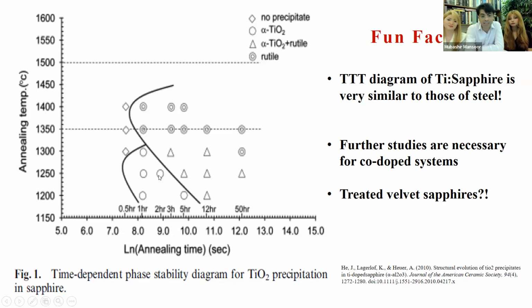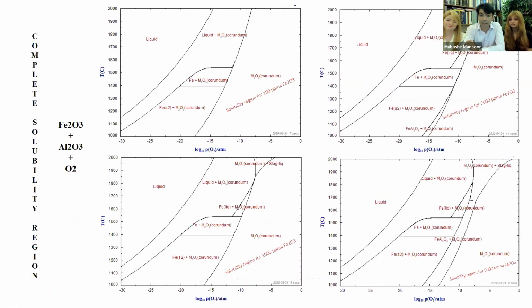You can use the same methodology to create star sapphires. So you have too much rutile, you go to a high temperature, you dissolve it all, and then you start cooling very slowly, and then you create these rutile crystals that contribute towards asterism. So it's all about how you treat and how you cool. It's basically all about designing the appropriate parameters for the experimentation process. Exactly. Now, we mentioned iron.